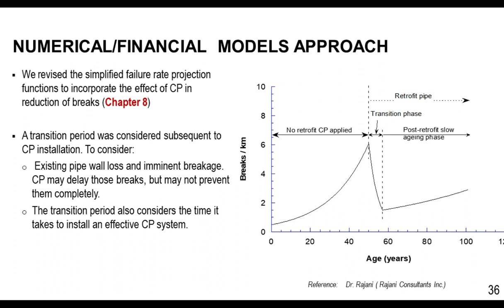But then after application of CP, there is going to be a transition phase or transition period before we see a significant reduction in the overall breaks. And after CP, the pipe will continue aging, but at a lower rate.